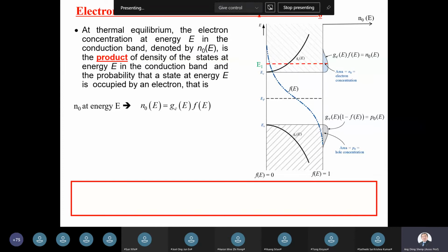Now the second point you should take note of is that the light having the strongest intensity being emitted does not come from recombination involving an electron at EC and a hole at EV. In fact, you have very few electrons exactly at EC. In fact, it is 0. If you go slightly above EC, there are very few electrons. Likewise, if you go slightly below EV, there are very few holes. So the intensity of the light coming from the recombination involving these carriers is very weak.